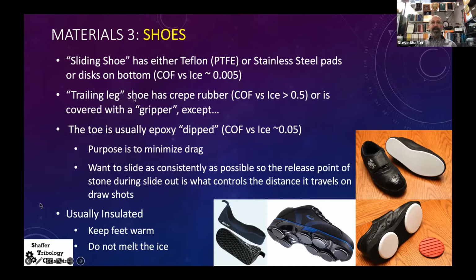The trailing leg, on the other hand, has a gripper. It's made of crepe rubber. You can see those here. And that has a much higher coefficient of friction, like 0.5. And that's so we can get up and down the ice without killing ourselves. Although the really good or experienced curlers, you'll see them sort of skating, and they're just pushing with the gripper foot and just sliding on their Teflon foot.